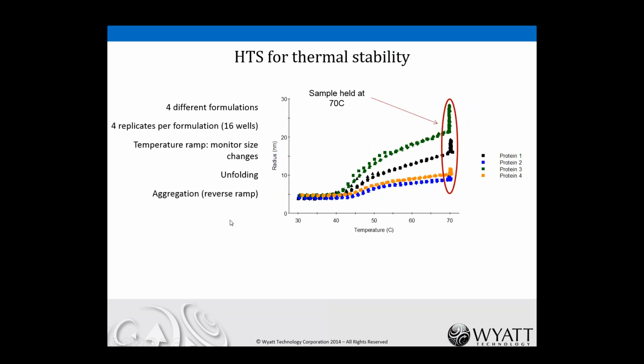Here's another example of high-throughput screening where we're looking at similar information for some different protein formulations. And here you can see that the temperature was held at 70 degrees, and depending on the formulation, you got different rates of aggregation. So essentially over time, you get up to 70, and then you just hold, and the size increases, which is an indication of the increased aggregation. So at the early stages here, there's a small change in radius, and that corresponds to unfolding. Later on, we get to aggregation.